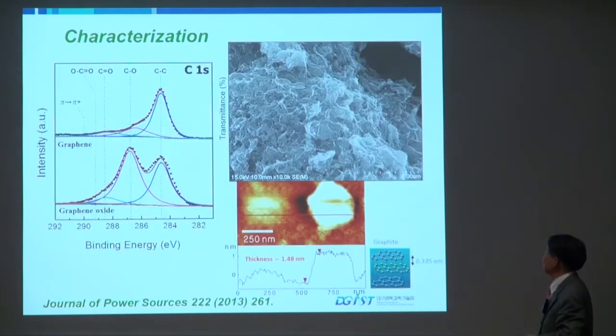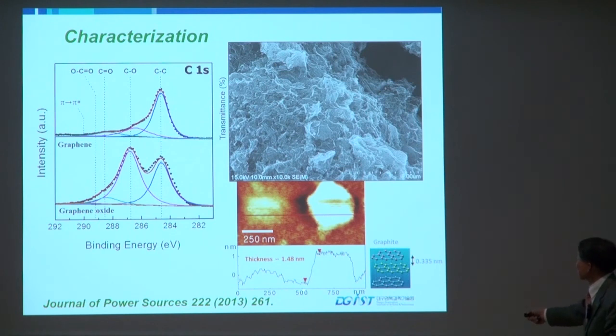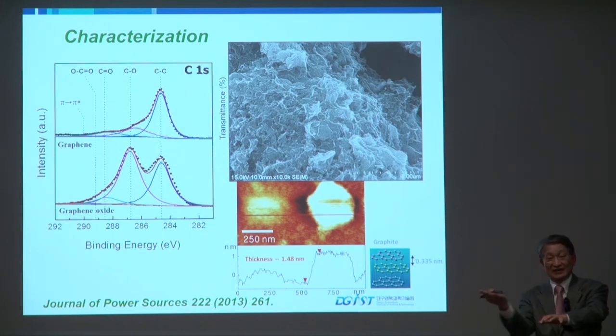Okay, then actually this is the morphology of the graphene, and you can see this is a very rough surface. And when you have graphene, same images, I'm going to show next, it's very flat. And also by AFM images, sometimes you have about 1.5 nanometers, and the graphene stacking is about 0.3 nanometers. So this is perhaps due to this huge Vulcan activated carbon in between graphene nanosheets.